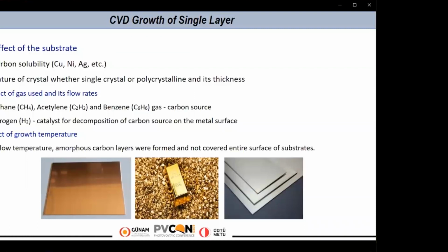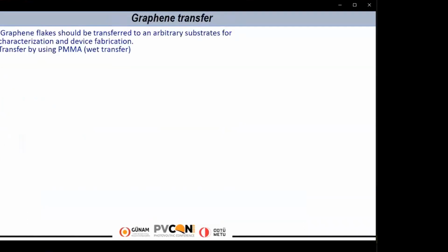We used polycrystal copper as substrate. A 30 minute growth time was applied at 1000 degrees Celsius for single layer graphene synthesis. On the other hand, the graphene layer should be transparent for solar cell application, so for the transfer we are using a wet transfer technique, which is called polymer supported transfer. The polymer we use is PMMA.